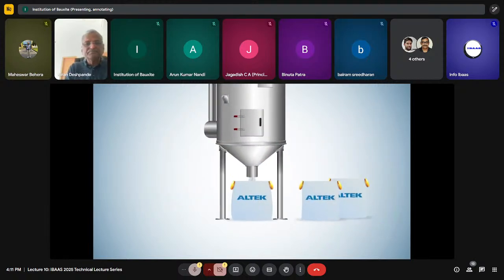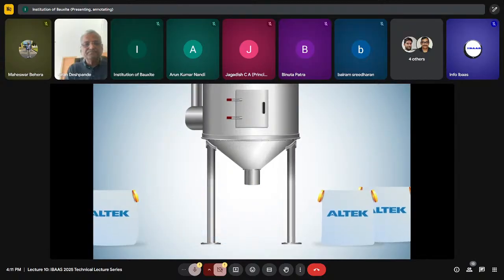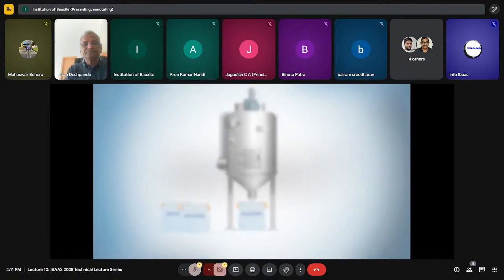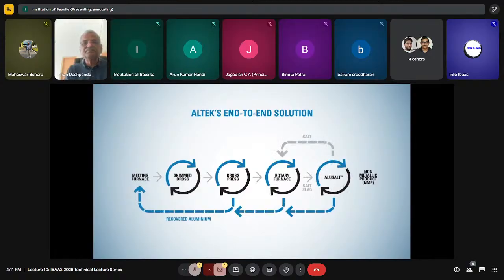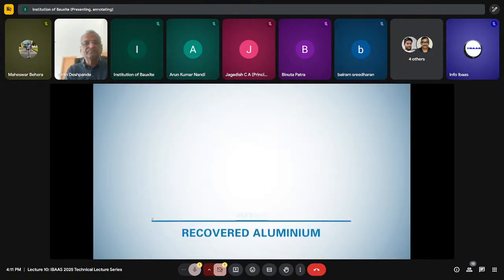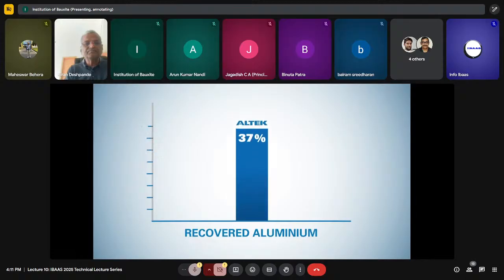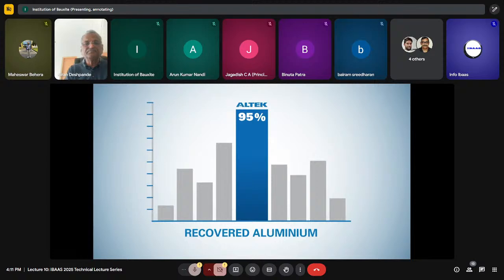Meanwhile, the extracted salt water is fed into a crystallizer, where the water content is evaporated off, leaving only crystallized salt. The recovered salt is collected and can be immediately reused in the tilt rotary furnace as a salt flux, again and again. ALTEK's multi-stage total dross management process recovers up to 95% of available aluminium from the dross, the highest aluminium recovery when compared to other competing technologies.